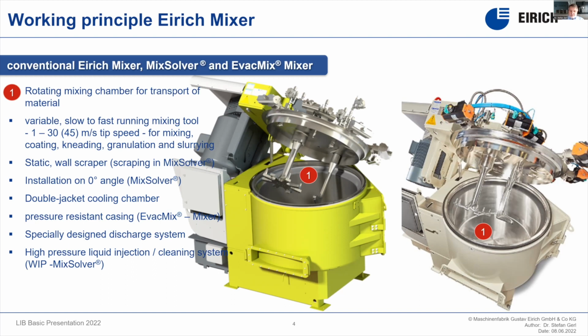And in the Eirich mixer, the movable or rotating mixing chamber now takes care of the transportation, so that we can work independently with our eccentrically mounted mixing tool. So we are free now to choose the shape of the tool. We are free to choose the speed, which can be very gentle and soft, or very aggressive. We typically operate our machines up to 30 meters per second. For dry battery application, we can go even up to 45 meters per second. And this is not only in the small scale machine, but also in full scale production machines. We have a static wall and bottom deflector or scraper, which was made really scraping for the battery application to make sure that we have no powder or plastic body adhesions on the wall or bottom, to be sure that 100% of the solids are really incorporated into the final slurry.